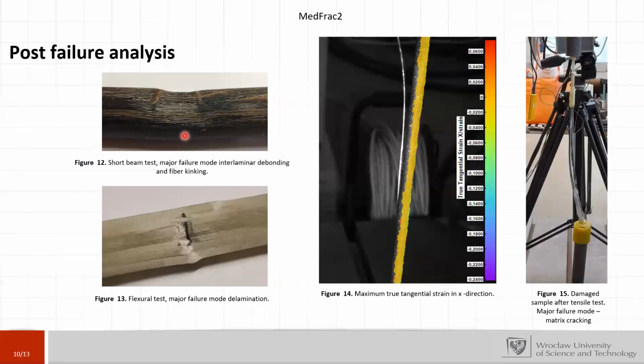Okay, so post-failure analysis. We noticed that during the short beam test, the major failure was the interlaminar debonding and also the fiber kinking. In case of the flexural test, the major failure mode was the delamination and the fiber breakage on the outer surface, the surface which was in tension. Here we see the strain distribution along the bar, and it's a screenshot from the DIC software. And figure 15 shows the damaged sample after a tensile test, and in this case it was matrix cracking and fiber breakage.